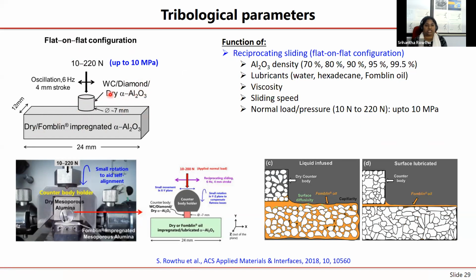Sorry, excuse me. Mostly I went with dry alumina samples. In only a couple of tests, I went with a diamond counter body. Here the bottom is impregnated while the top is not impregnated. That's why we call it a dry specimen. Then the loading is between 10 and 220 Newton. That is the full range of the tribometer. It's an SRV tribometer that I have used in Switzerland, and that means the pressure is up to around 10 megapascals. And this is the real digital image of how the holders look.